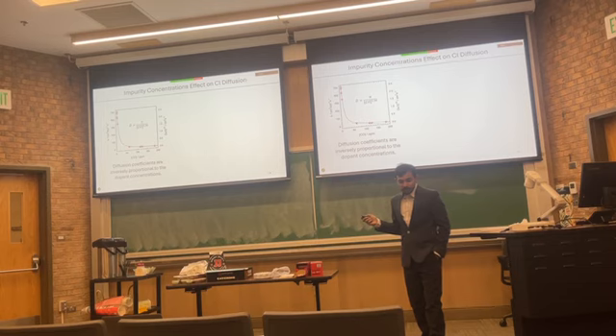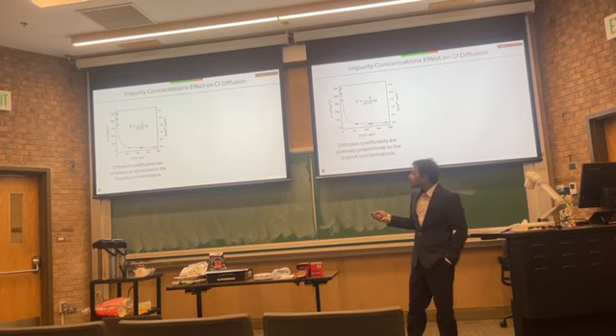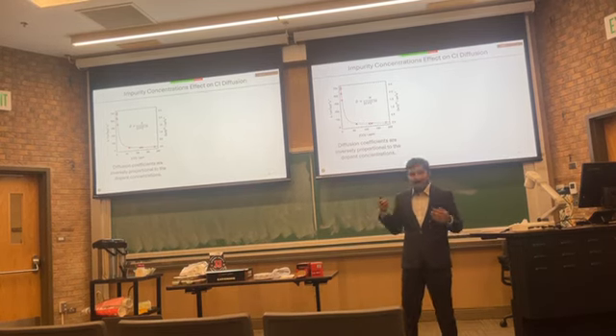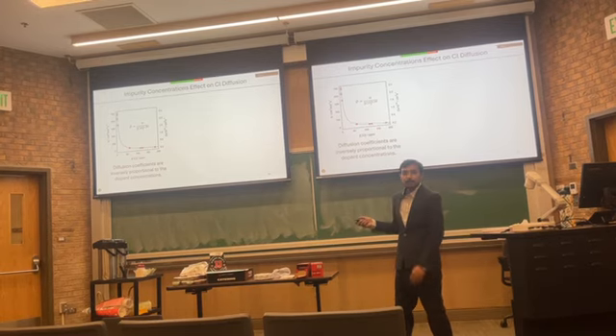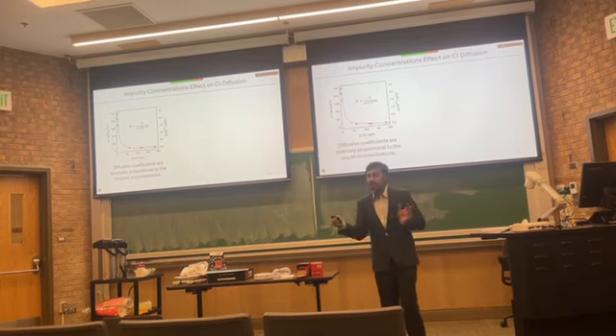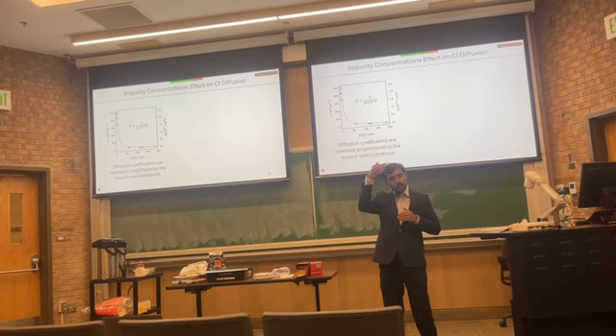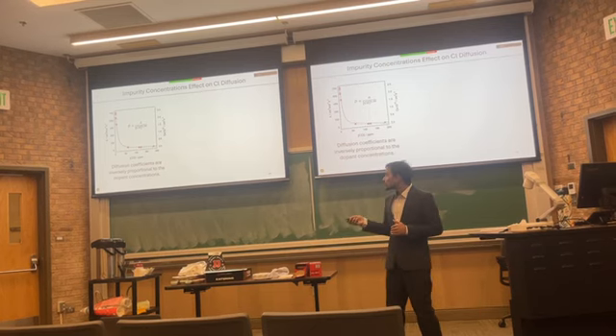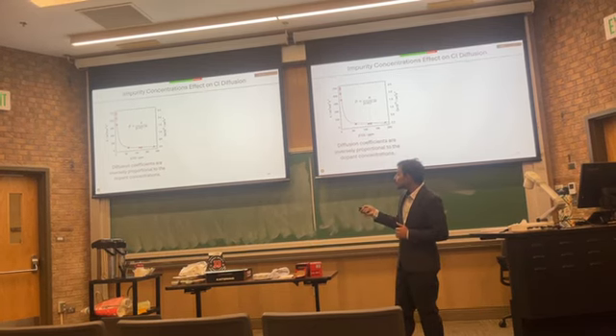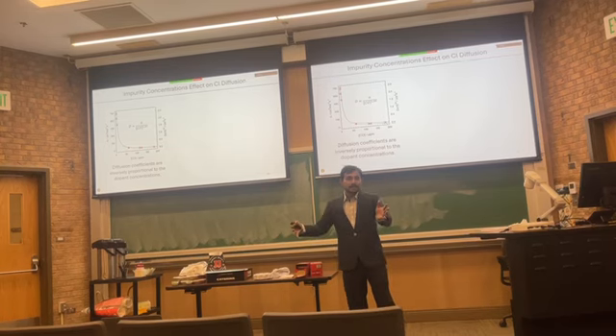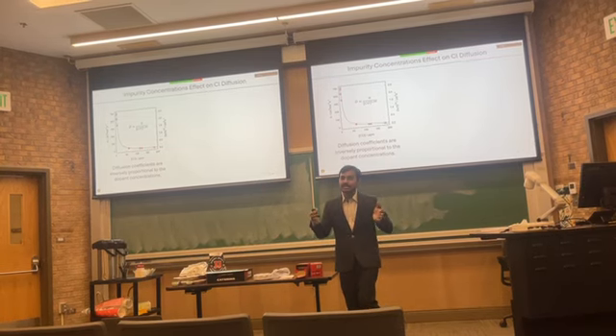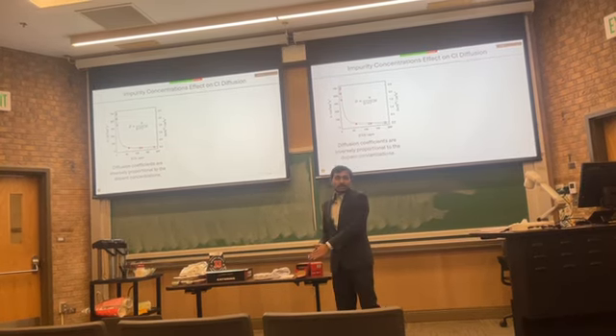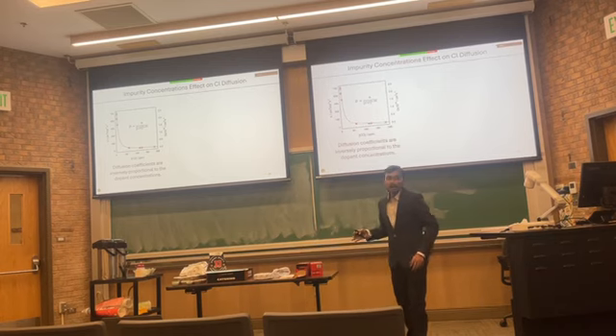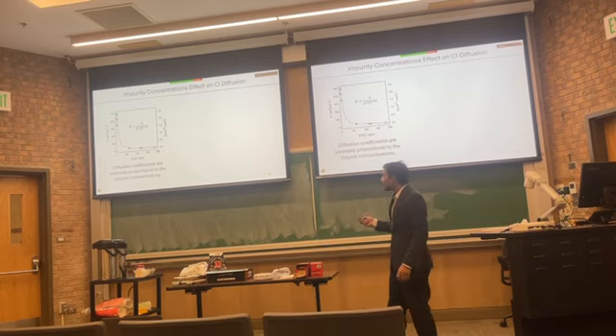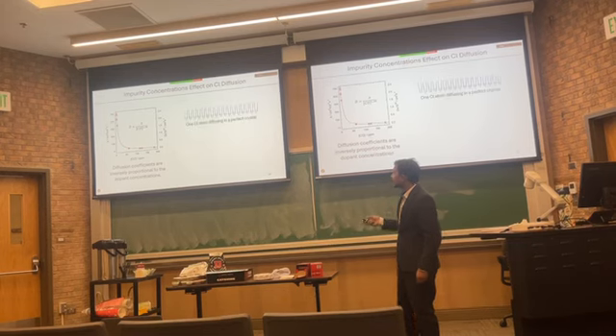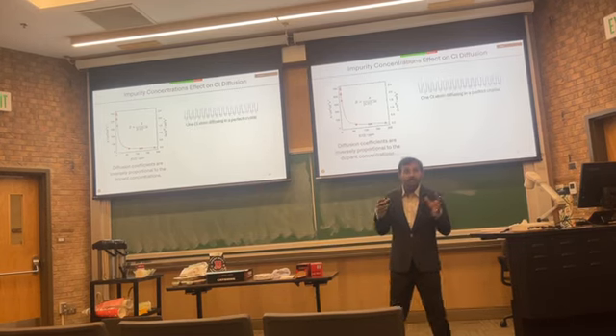What we have found is that if we plot those diffusion coefficients or rate constants against our impurity concentration or dopant concentration in the system, we see that our diffusion coefficient goes down. So this is inversely proportional. If you increase the concentration of the reactants in the system, the reaction slows down. This is never going to happen in classical kinetics, but why did this happen? We think what's happening is quantum tunneling.